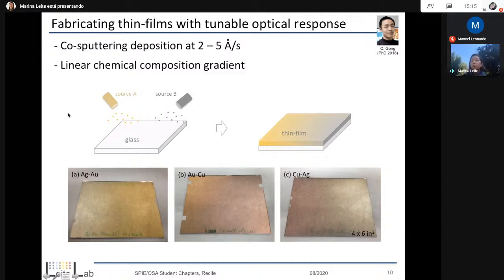So the first thing we did was to fabricate thin films with a very narrow and well-controlled gradient in chemical composition. So that's what you're seeing here: by sputtering, later I have a video on sputtering, but for now you have to believe me that I have this spray of atoms from two metallic sources, and that by co-depositing without rotating the substrate, we could obtain films that were from pure silver, for example, all the way to pure gold, and the same for gold and copper, and copper and silver, as you can see here in the slides.